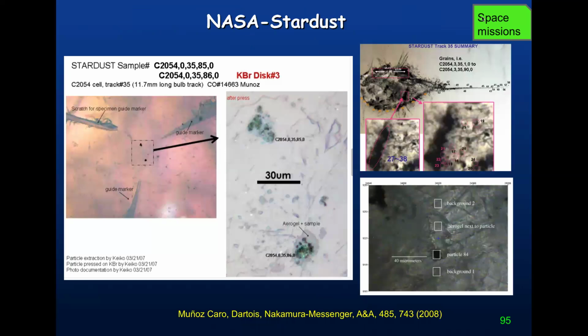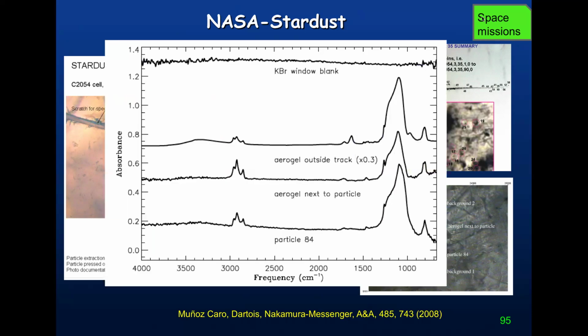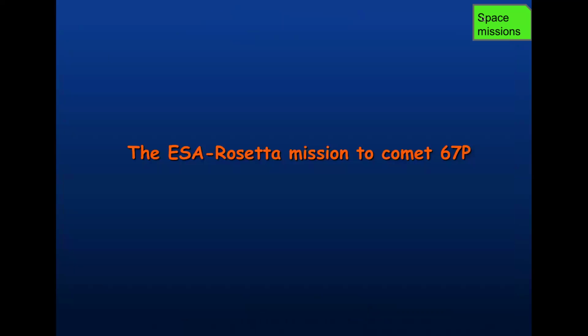And I also got NASA Stardust particles when I was already in Spain. I got 6 of these particles, and we did infrared spectroscopy on them. These are the spectra. They are characteristic of amorphous carbon, but we doubted whether it was indigenous from the comet or some contamination in the aerogel.